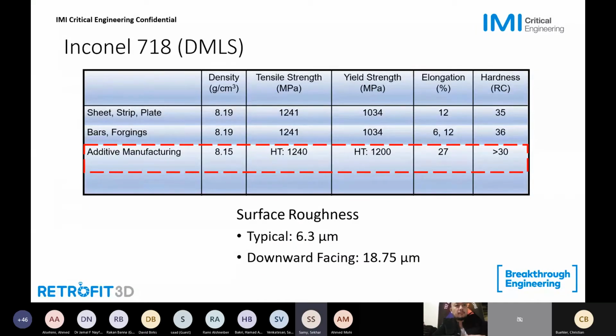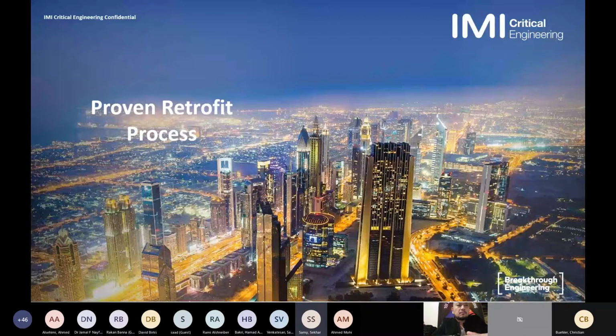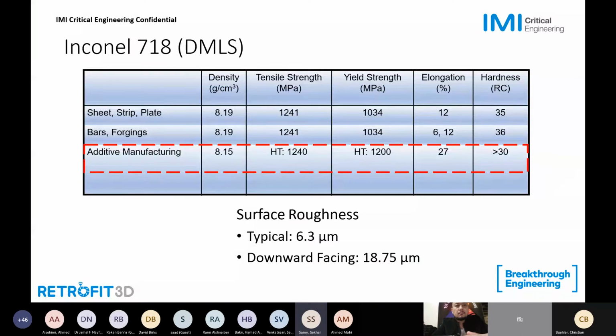Here are typical additive manufacturing properties over many, many tests that we have done. The tensile strength is normally around 1240, so it's very, very close to the spec of 1241. The yield stress is slightly higher, about 1200 megapascals compared to 1034. The elongation is actually extremely good, about 27%. The hardness, which is really a function of further heat treat that you can do, is greater than 30. The surface roughness is also slightly different depending upon how you print it. If you have a roof that you're printing, it has a slightly higher surface roughness, about 19 micrometers. And if you have something that is vertical, then you get about 6.3. Next slide.